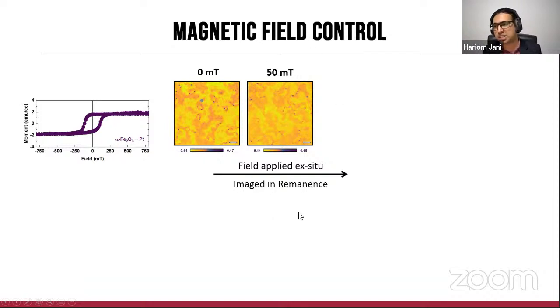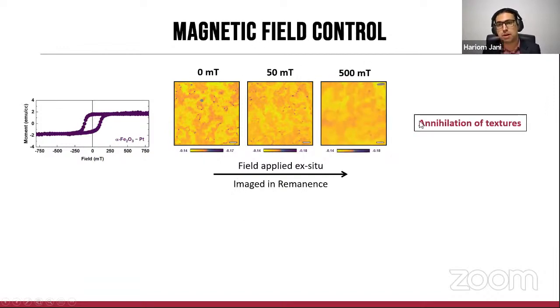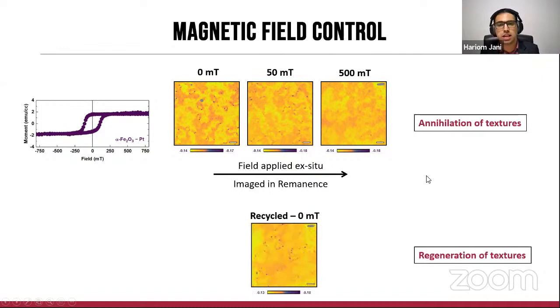This is quite interesting because it may be possible that some of the ferromagnetic objects may have already annihilated here, but antiferromagnets in Fe2O3 survive. But of course, if you apply extremely large fields where you start to realign significant fractions, you would still end up annihilating some of these textures in Fe2O3. There are, of course, ways to extend this number and shift this anisotropy, which is really a materials engineering term. But what I'm trying to show here is that it is possible to use magnetic field as an annihilating mechanism, but only very strong fields.